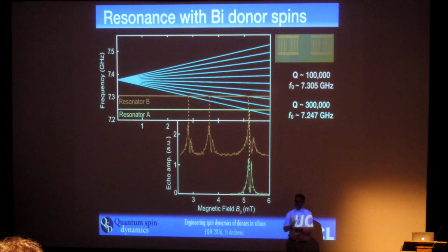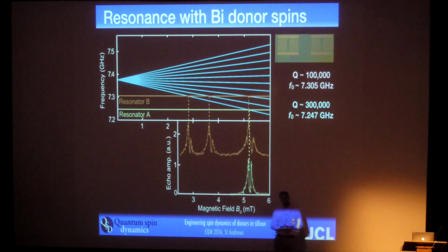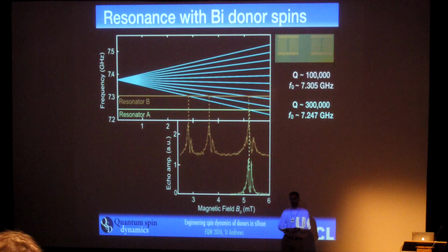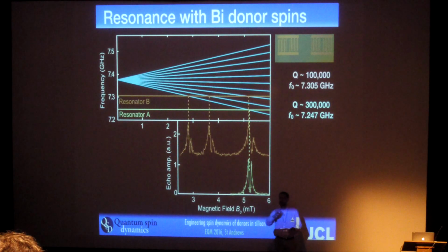For the strongly coupled dopants, you see a transition frequency right in the middle of the spectrum, which has effectively zero hyperfine coupling. So far, all experiments have been done on randomly doped samples, so you have a range of exchange couplings, and you try to pick out different regimes based on the transition frequency. But eventually, in the future, one could try to engineer regular arrays with stronger couplings.